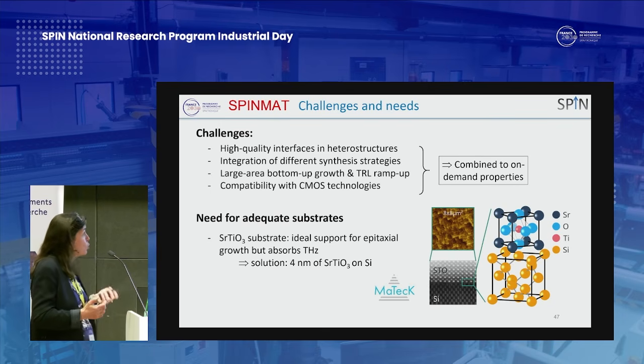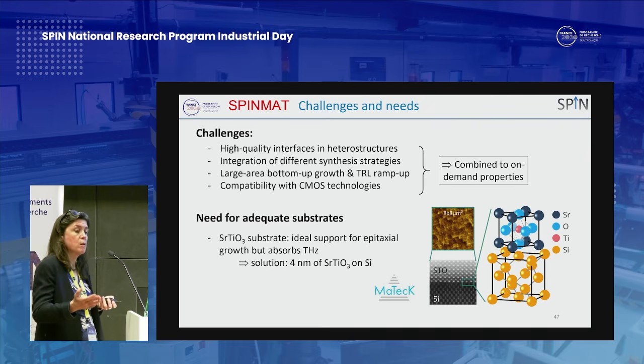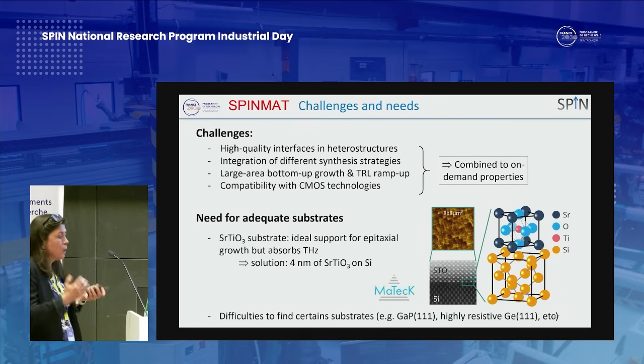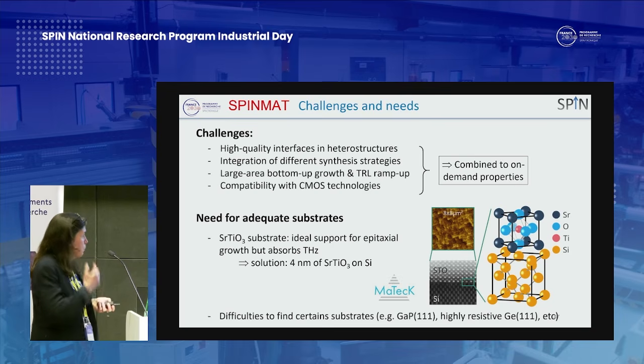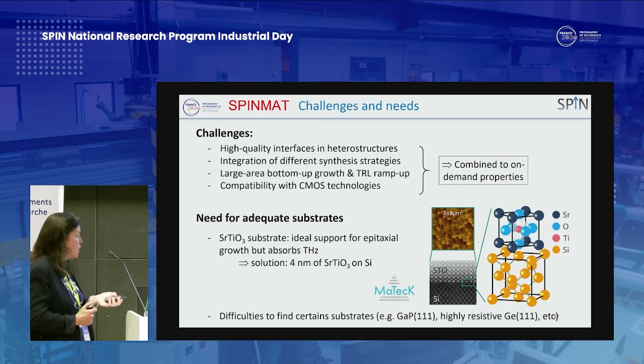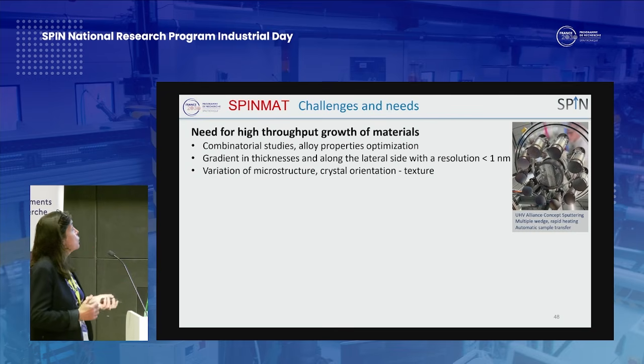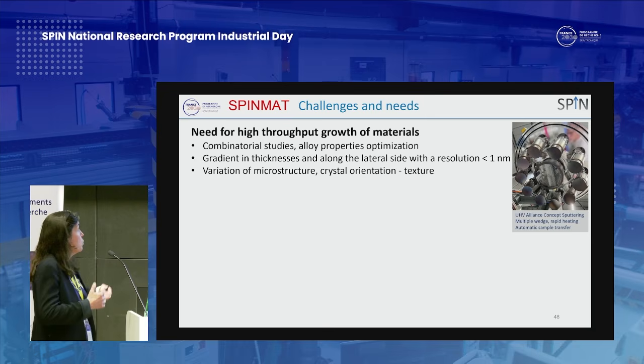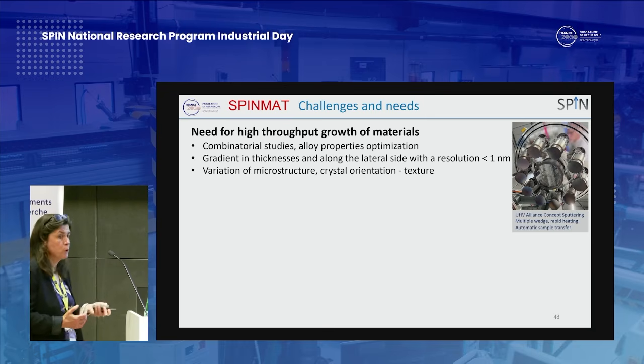And Matec, for example, developed a solution: a silicon substrate with an epilayer of 4 nanometers of STO for subsequent growth. But that is a solution for one case; for other cases, it's difficult to find certain substrates, such as GaP 111, germanium 111, NGO 111, and so on. We also need high throughput growth of material for combinatorial study, alloy property optimization, to get a gradient of thickness with sub-nanometer resolution, to also study the impact of the microstructure.